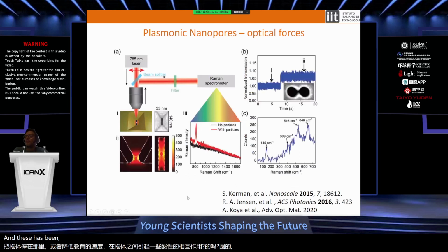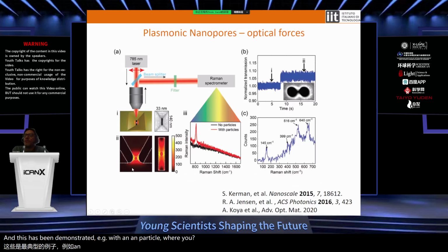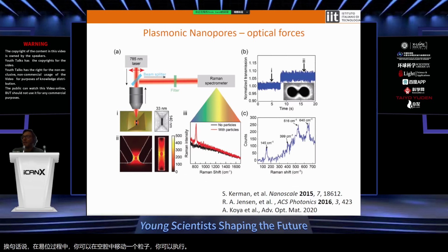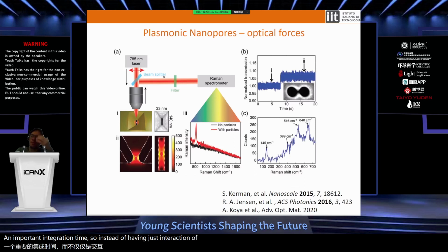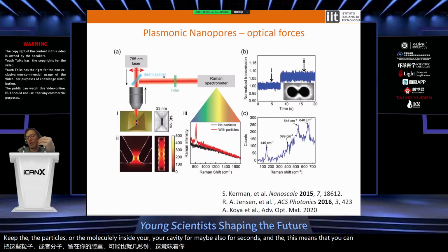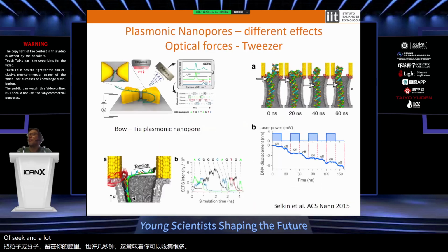This has been demonstrated, for example, with a nanoparticle, where during the translocation you can trap the nanoparticle in the cavity and perform enhanced spectroscopy with an important integration time. So instead of having just the interaction for a few microseconds, you can keep the particle or the molecule inside your cavity maybe even for seconds, and this means that you can collect a lot of signal and a lot of information.